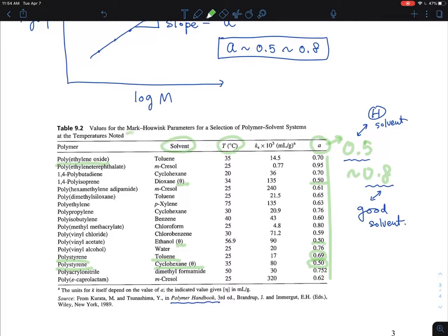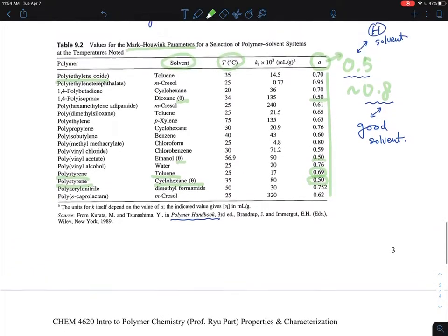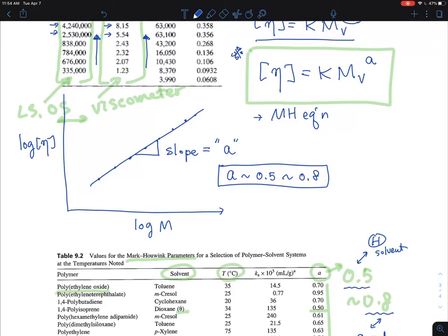And these are Mark-Houwink parameters, and they're very powerful and widely used for correlating that. Essentially, the higher the molecular weight, the higher the intrinsic viscosity. And that correlation was found here. Later, people found a meaning for this power law exponent A, and also for K, to a lesser extent, and found a way to correlate them to something more fundamental, what we call the solvent quality.